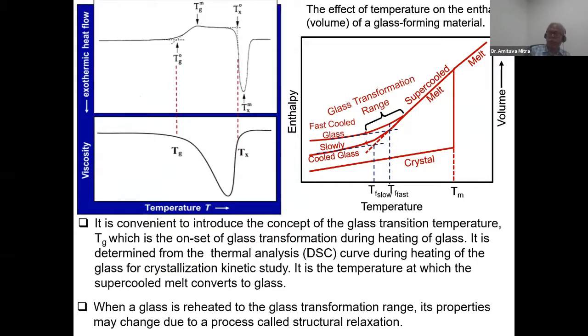How can we determine this temperature? This temperature is determined by thermal analysis, differential thermal analysis, that is DSC, and this is the DSC curve. You see, at this point there will be an endothermic peak, and then there is an exothermic peak.